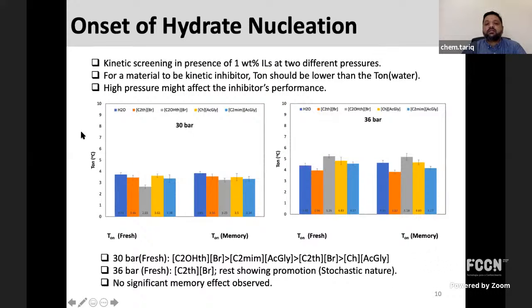So we assume that there are some nuclei of the hydrates still existing in the system. Then these are the results for onset of hydrate nucleation in presence of 1 weight% ionic liquids, because we want to propose these ionic liquids as LDHIs. So it should be in between just 1 weight% to 3 weight%. So for a material to be a kinetic inhibitor, the onset of nucleation temperature should be lower than the water onset temperature.